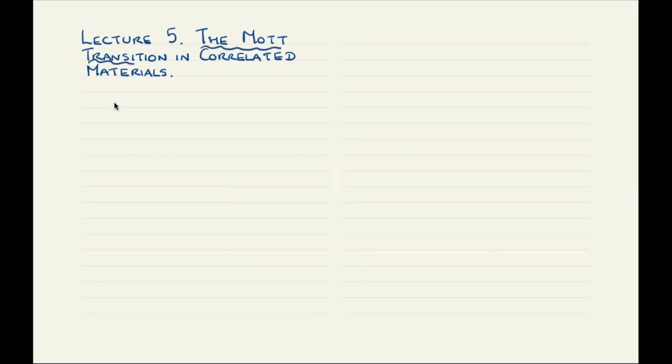In this lecture, we'll look at two examples of strongly correlated materials that have a metal insulator transition, which is attributed to a Mott transition. We'll look at the examples of the rare earth nickelates and of vanadium O2. I've chosen these examples because in both cases, it's difficult to say for sure that the main physics is coming from the Mott transition, because there are other competing or cooperating factors which also might contribute to the metal insulator behavior, and it's difficult to say precisely which one dominates in which case.